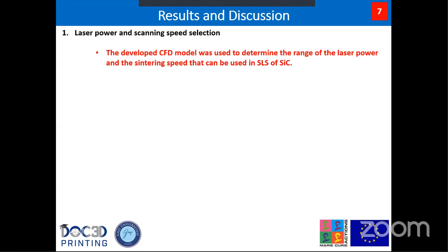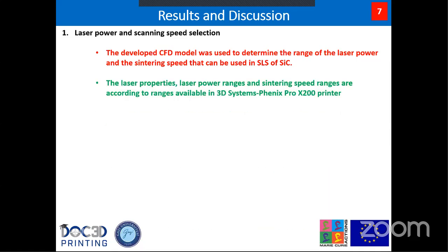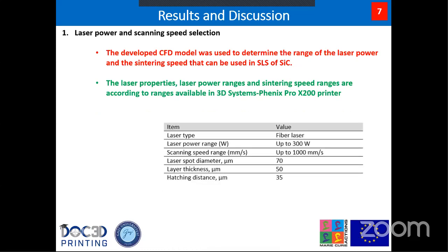For the result and discussion, first we studied the laser power and the scanning speed that can be used in SLS of silicon carbide, where we used a range of laser power and scanning speed according to the printer manufactured by 3D Systems company. The laser type used in this printer is a fiber laser, with laser power up to 300 watt and scanning speed up to 1000 millimeter per second. Laser spot diameter is 70 micrometer, the layer thickness used in the model is 50 micrometer, and the hatching distance is 35 micrometer.